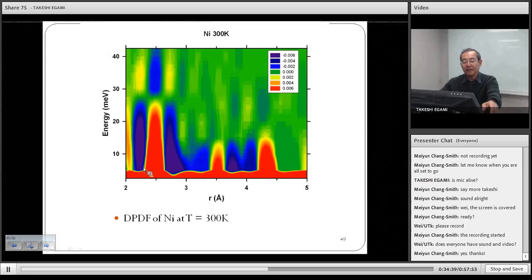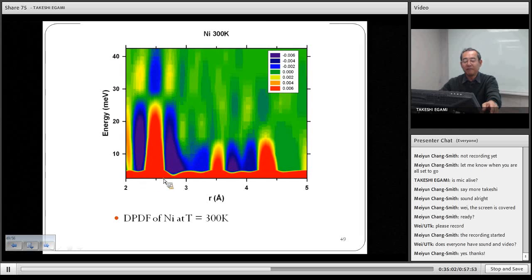Here, this peak is due to the first nearest neighbor. We are looking at nickel, FCC nickel, at room temperature. So 2.5 angstrom is the distance of nearest neighbor. And then the second nearest neighbor is this guy, and then the third nearest neighbor is this guy. So as you can see, the low frequency phonons are just represented by a peak. But high frequency phonons are split.